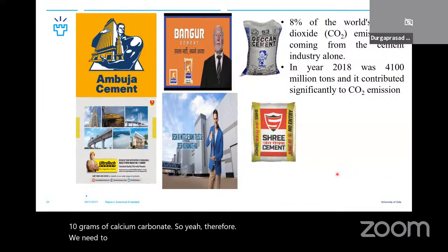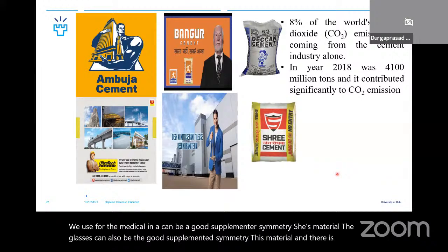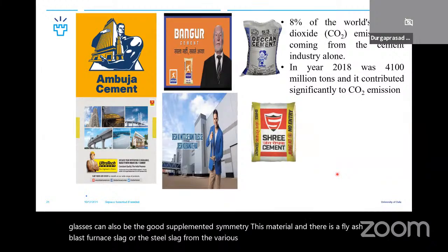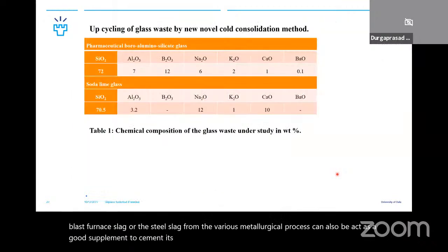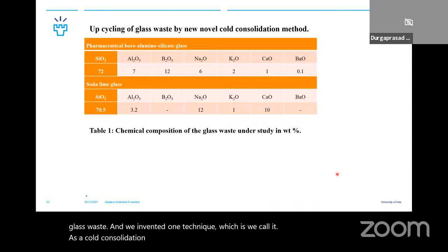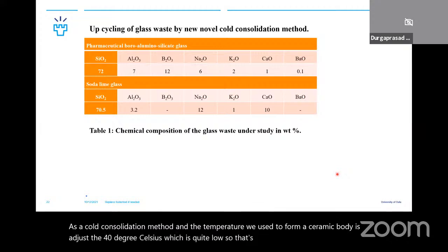Therefore, we need to find another supplementary cementitious material. For that, metakaolin, Multani Mitti, the common term we use for metakaolin, can be a good supplementary cementitious material. Glasses can also be good supplementary cementitious materials, and fly ash, blast furnace slag, or steel slag from various metallurgical processes can also act as good ones. So we decided to do some upcycling of glass waste, and we invented a technique which we call the cold consolidation method. The temperature we use to form a ceramic body is only up to 40 degrees Celsius, which is quite low. That's why we term it cold consolidation.